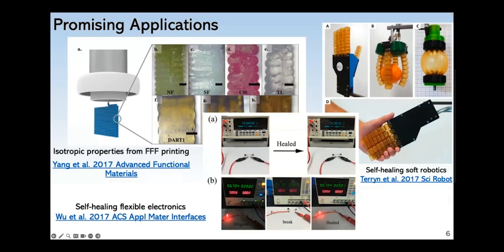And DA materials, on the other hand, can form homogeneous layers because of their forward and reverse reactions occurring simultaneously to form chemical bonds between the layers. In this middle set of images, the researchers constructed a conductor out of Diels-Alder material, and then they spliced it and then healed it with just heat and showed that the conductor was able to light up the LED again, which just goes to show how well these materials can heal.